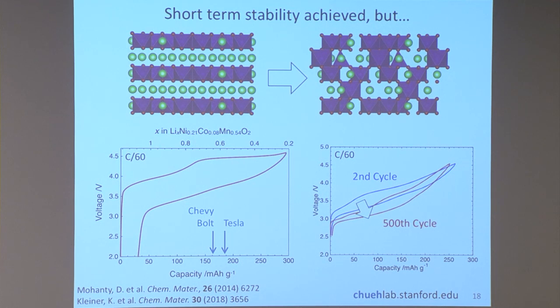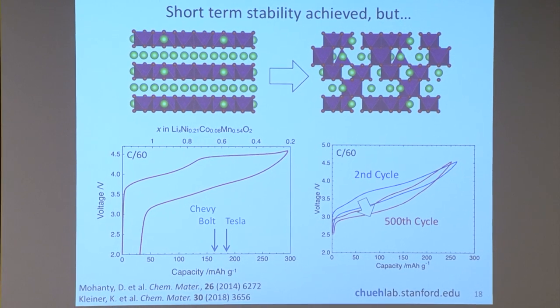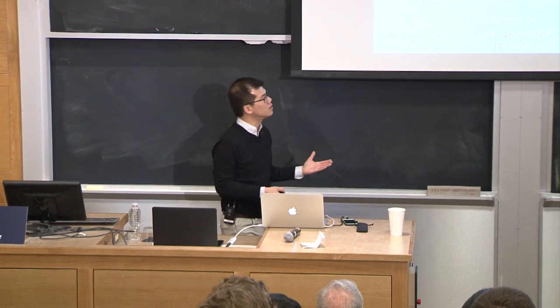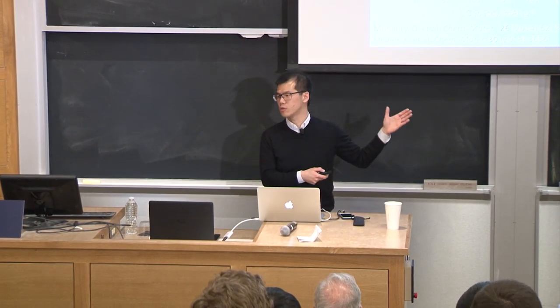But as you can see, there is still strong hysteresis and degradation. The integral of this curve is the energy output of the battery. So as the voltage keeps falling, the material is degrading. So we wanted to understand, one, what is happening in this battery material as you overstuff it with lithium? How does this lithium-oxygen bond help stabilize the material? And then two, why is there still structural transformation?